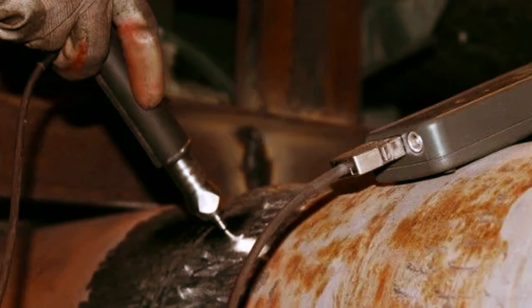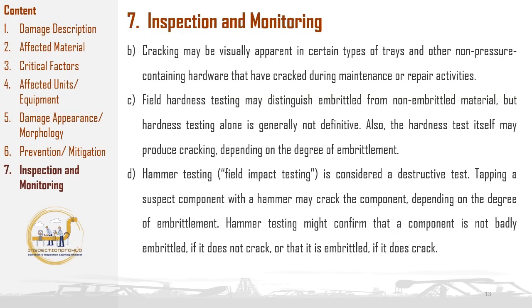Field hardness testing offers a potential means of distinguishing between embrittled and non-embrittled materials. However, it's important to note that hardness testing alone is generally not definitive in diagnosing 885 degrees Fahrenheit embrittlement. Moreover, the hardness test itself can potentially induce cracking in severely embrittled materials, adding a layer of complexity to this inspection method.